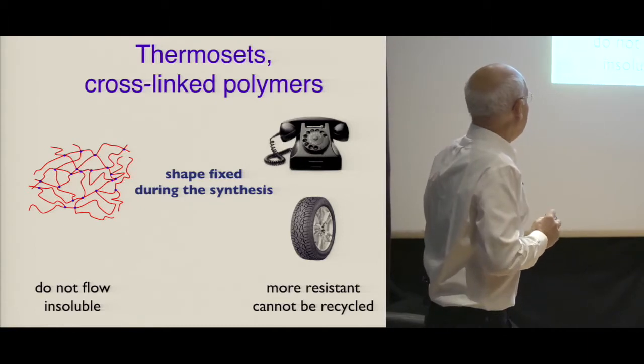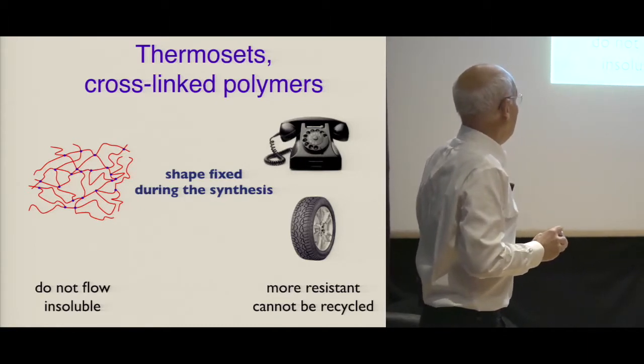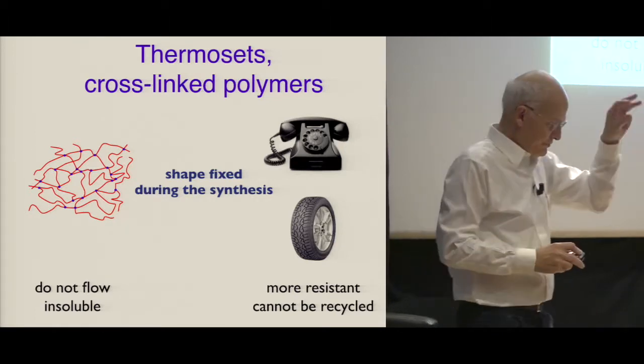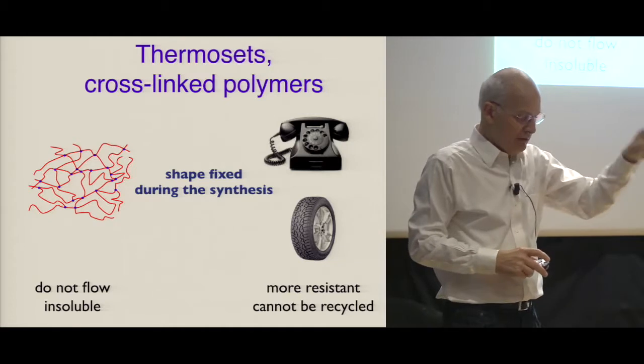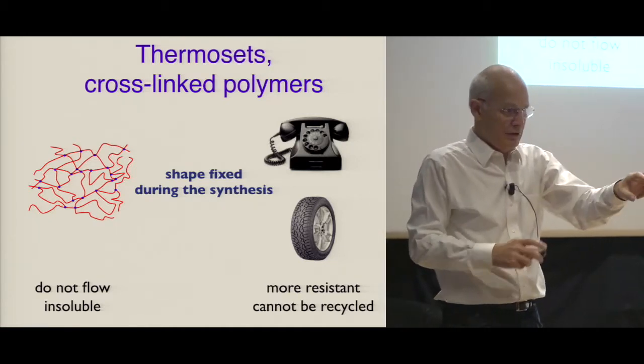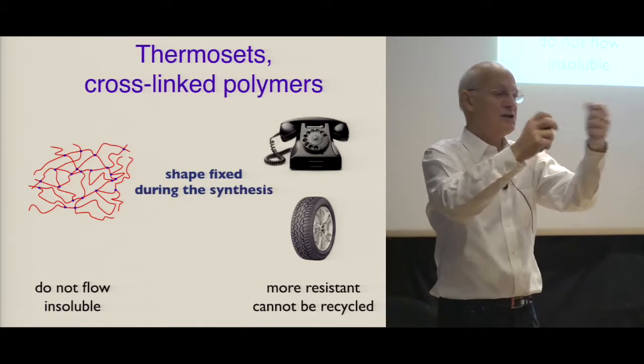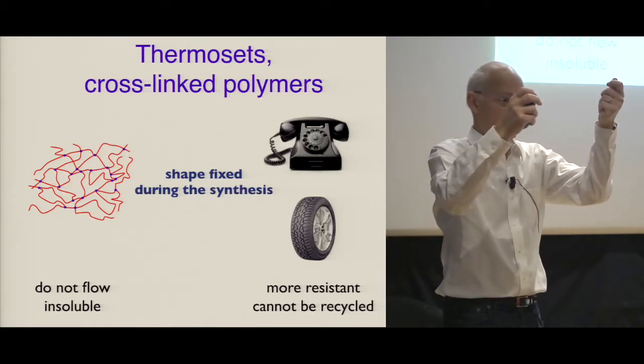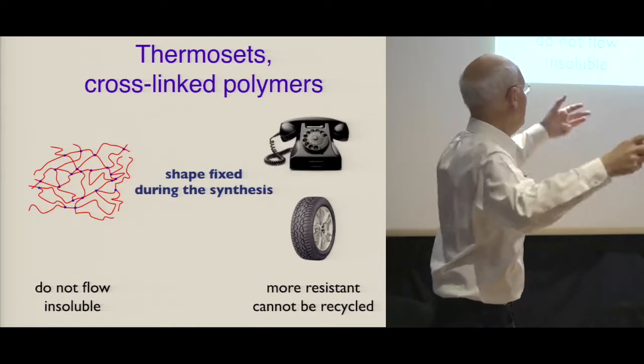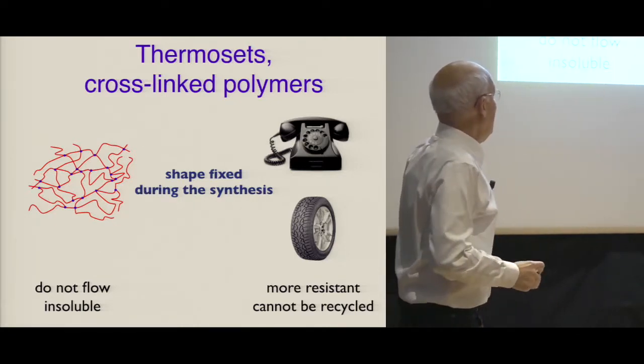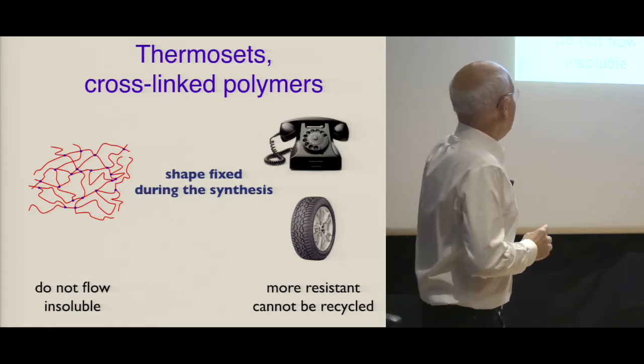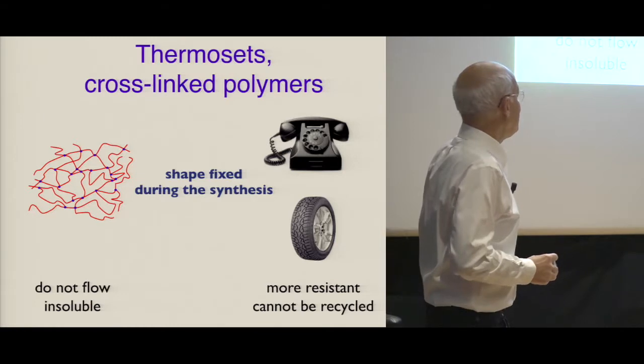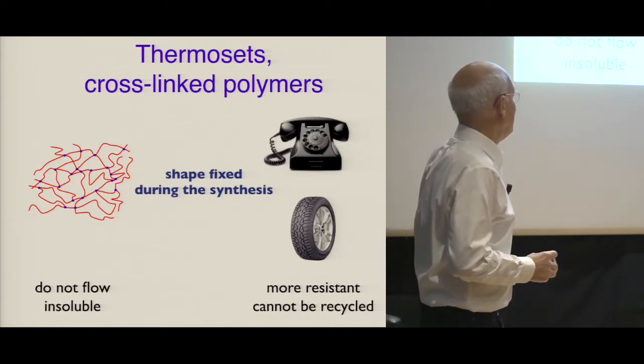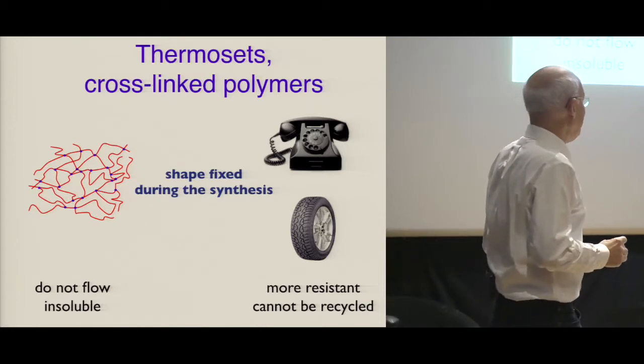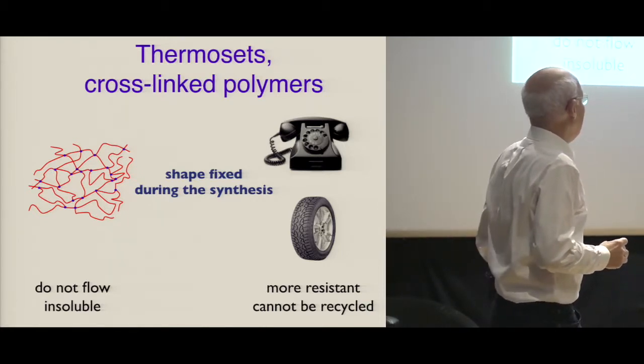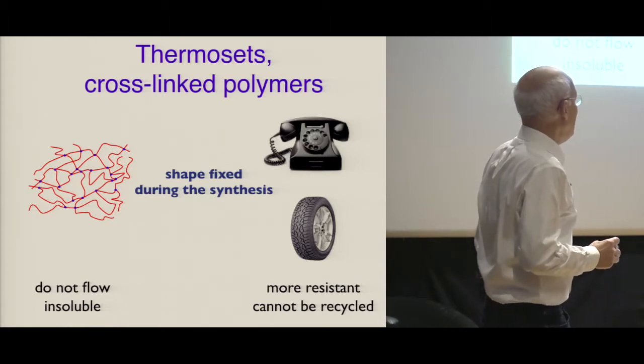And so when you prepare these objects, like the tire, you have to shape the object during the synthesis. And once you fix the shape, you cannot remold it. By heating, it will not flow. You cannot put it in a solution because, again, it will swell, but it will not flow. And this might be a problem. However, these materials can be much more resistant. They have better mechanical resistance, chemical resistance, resistance to solvent, and they have good dimensional stability.